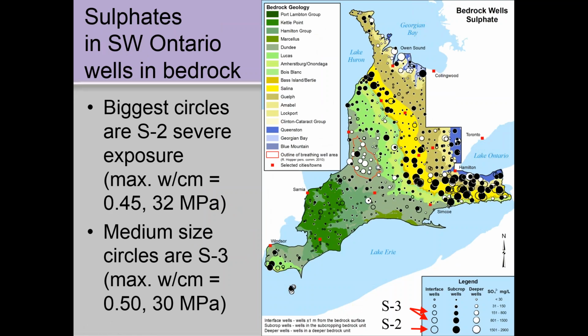But this is a map I was able to find with sulfate contents of well water in southwestern Ontario. Unfortunately, I don't have it for the rest of Ontario, but right along the escarpment line, you can see these big black circles. And those are the ones that are severe, up to almost 3,000 ppm, or milligrams per liter sulfates in the water. So there are sulfate soils right up through there.